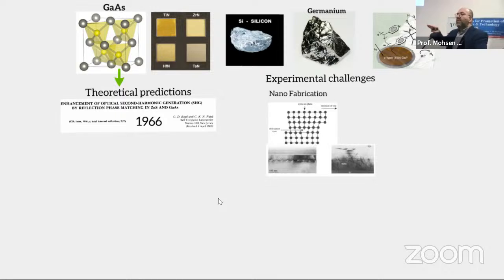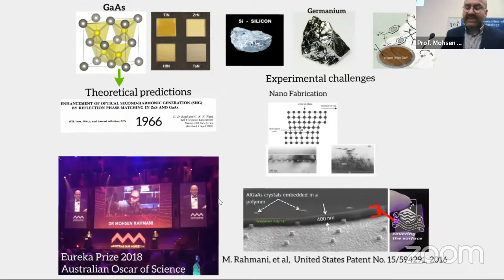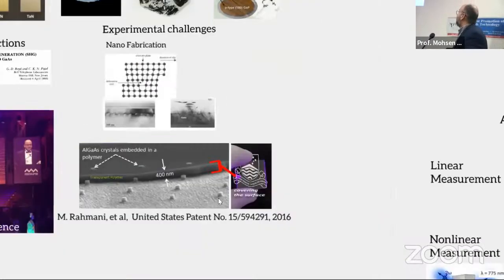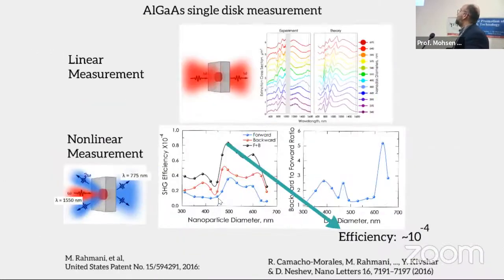Understand that we can have the buffer layer, but still the handle wafer of all of these buffer layers, like gallium arsenide or indium phosphide, is not transparent in the visible light, so they are not usable for us. So in general, I invented this technique to fabricate them on the gallium arsenide itself, then transfer them to the glass. So we managed to get them, and we managed to increase the efficiency.